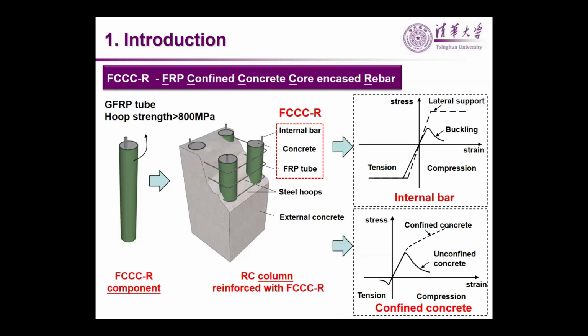The FCCC-R is composed of the internal high-strength steel bars, the filled high-strength concrete, and the external FRP tube, as shown in the figure. Well, for this component, the compressive strength and ductility of the filled concrete are enhanced due to the lateral confinement effect of the FRP tube, and cracking and spalling of the concrete is then prevented. Thus, the local buckling of the rebar can be prevented under compression due to the lateral support of the concrete. So the problem of the strength loss of the high-strength rebar buckling and the poor ductility of the high-strength concrete can be avoided. In this way, this new component shows great mechanical performance under either compression or tension, which can be regarded as a high-performance composite bar.